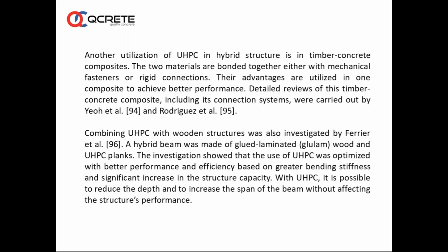The investigation showed that the use of UHPC was optimized with better performance and efficiency based on greater bending stiffness and significant increase in structure capacity. With UHPC, it is possible to reduce the depth and to increase the span of the beam without affecting the structure's performance.